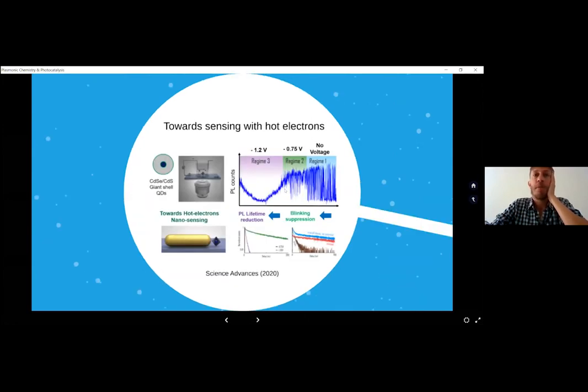And the very last example before I finish is something that we started working on recently, and it's the idea of how we can sense the hot electrons in these plasmonic materials. For that, we have been working on the idea of having quantum dots in an electrochemical cell. What we have seen is that quantum dots can be charged with electrons when you change the voltage. When you apply a voltage in this electrochemical cell, the optical properties, the emission, for example, the PL lifetime or the blinking of these quantum dots, can be strongly modified by the amount of carriers being introduced into them.